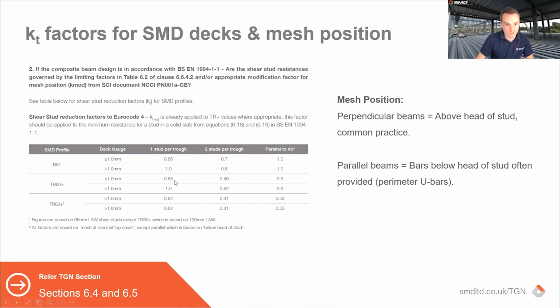To best show that, if you look at 1 stud per trough in a TR60 of less than 1 mil, we get 0.85. That's the reduction per stud. So it's not far off of a stud in a solid slab. If we move to 2 studs, because of the limitations in the code of how far the studs have to be apart, we only get 0.49 per stud. So 2 studs in a trough at the very closest centre in the code, which I'll come to in a moment, will only actually give us 0.98 in comparison to 0.85 of 1 stud. And I think that's quite important to realise, that putting 2 studs on doesn't give you double 1 stud. I'm going to move on a bit more onto that in a moment, but this was to just put some numbers to that.